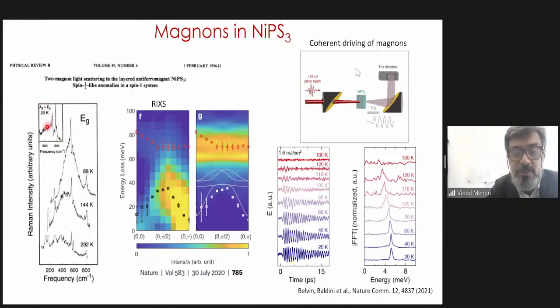So not just phonons, they looked at the Magnons as well. So these peaks that you're seeing here are the phonons. And then this broad peak that we're seeing is the Magnon peak. And so in Raman, you can't directly excite the Magnon. You need to use a 2-photon excitation type process. So it's the 2 Magnon excitation that we are seeing here. So that was this result.